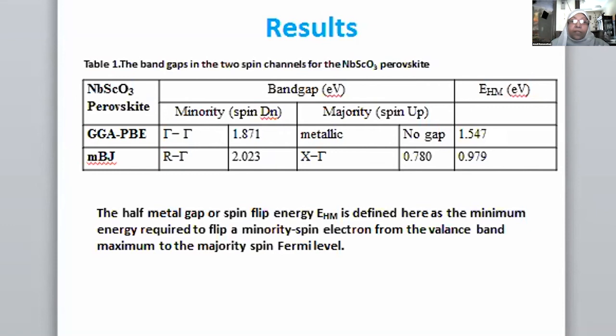So here in the case of MBJ, we are having about around 1 electron volt, and this is substantial. So for good spintronic materials, we need to have a large band gap, and that's the case here. And we need to have a large and substantial half metal gap too, for robustness of the device. So these results are very encouraging.